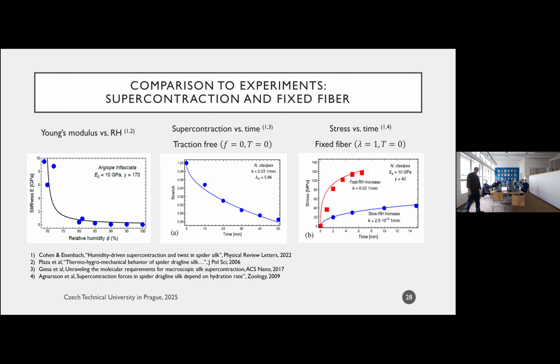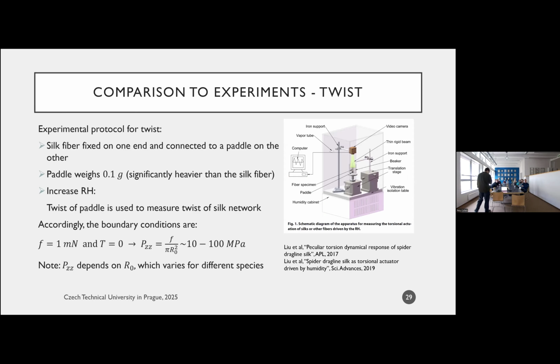So before I characterize the twist, I have to tell you how they measure the twist. So keep in mind, this is a fiber. The fiber itself has a diameter of micrometers. So it's not like you can draw a line on it and measure how much it twists, right? It's very difficult to see how to actually measure the fact that the fiber twists, just because of the scale of the system. And so in 2017, there was a paper that came out with a pretty clever design of how to measure the twist in these fibers.